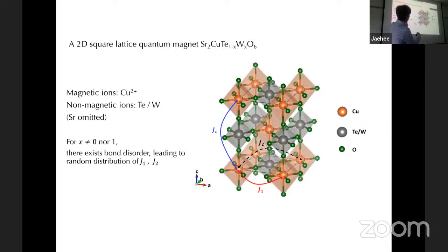And so since it's a superexchange going through tellurium or tungsten, this J term will depend on the wave function of tellurium and tungsten, right? And so if we have a tellurium case, it turned out J1 is strong, dominant, still antiferromagnetic. If it's tungsten, then J2 is dominant, still antiferromagnetic. Okay. But then why is it quasi two-dimensional?